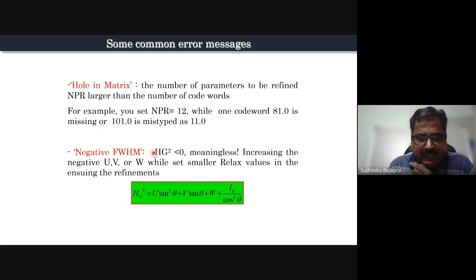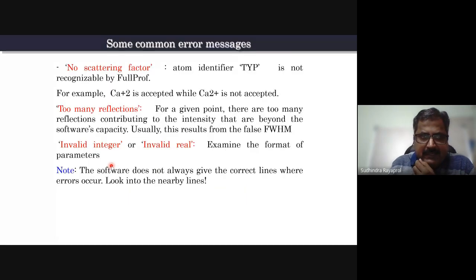And sometimes it gives a negative FWHM error also. So you have to see how the parameters are. It cannot be less than 0. It is meaningless. So you have to check the values and ensure that it is going in the proper direction. And there are certain other errors which you usually find, like no scattering factor. So you have to identify the atom type which is given, which is not recognizable by the program. Like I said, it can accept Ca+2, but it cannot accept Ca2+. Like that, it can give you certain errors. It will not tell you what is wrong. It will tell you that it has not found that element.